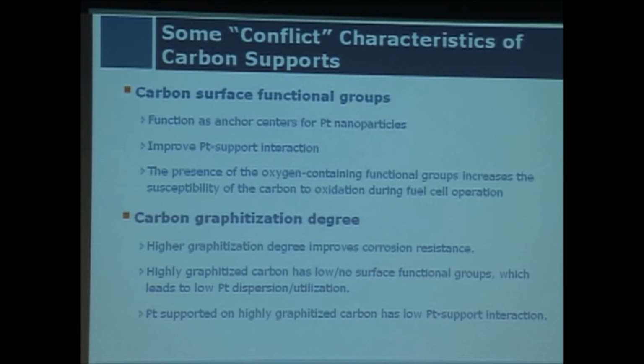For example, carbon functional groups. That is really good when you disperse the platinum onto it, because those functional groups function as anchor sites to hold the platinum there. So you can get very good dispersion of platinum, and also you improve the platinum-support interaction. However, most of these functional groups are oxygen-containing, so when they stay there, it's relatively easy for them to be further oxidized to carbon dioxide. In this case, that is bad, so it degrades faster.